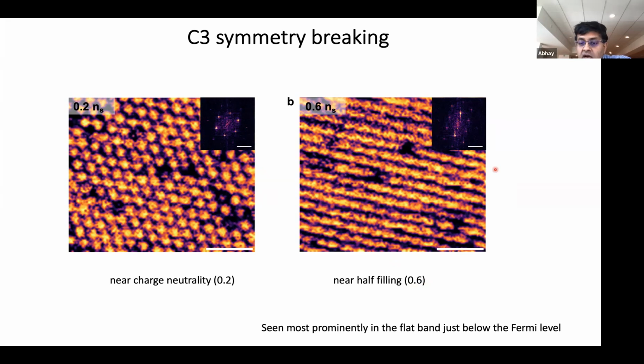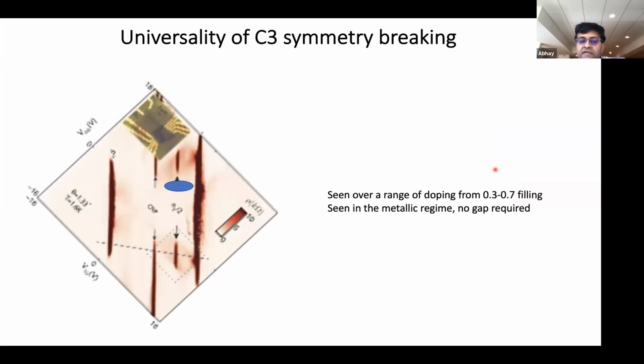And so this was sort of our primary finding, that this material has a nematic phase, and this nematic phase is not confined to a particular value of doping. It extends over a rather wide range of doping from about 0.3 to 0.7 filling of the Moiré unit cell. And importantly, it also exists when the system is not an insulator, when it's a metal. So very much like the case of the pnictides, where there's no real insulating state. This is a metal, and it exhibits this nematic behavior over a fairly large range of doping.